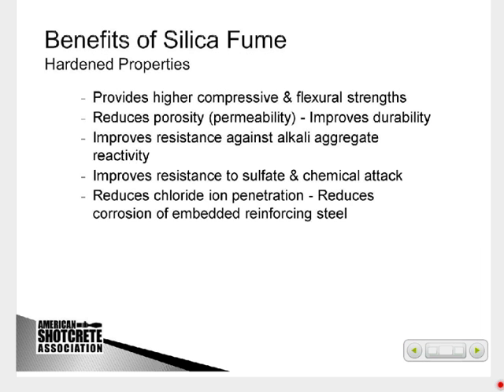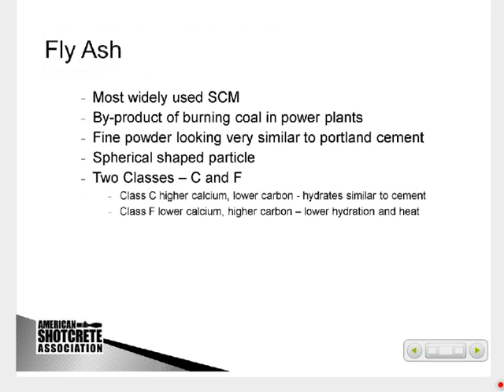It also improves compressive strength, flexural strength, improves durability because we reduce porosity. That gives you better resistance to chemical, sulfate attack, chloride ion penetration. We also can use other SCMs, fly ash, which you typically see in your cast-in-place work. It has a lot of benefits.